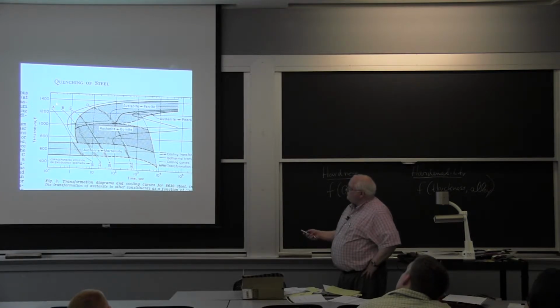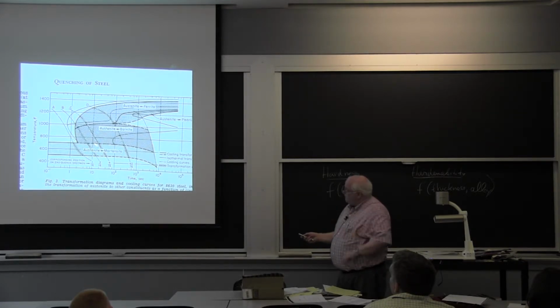This is for 8630 steel. I have to cool it down within less than a second to get 100% martensite. Okay, I might not transform all the austenite, which is the phase at high temperatures, but if I want to get my martensite, I've got to cool it down in less than a second. If I add alloying content to this, I can push what we call the nose of this curve all the way over. So this is the transformation curve.